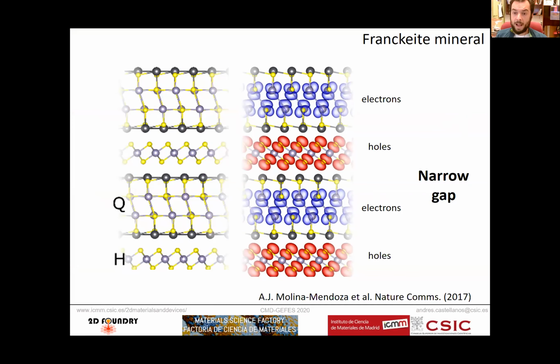One of the first things that you have in this franckeite is, for instance, a very narrow bandgap semiconductor. If you calculate the band structure with DFT, you get a really narrow bandgap. And this is shocking because a monolayer of tin sulfide has a bandgap of more than 2 electron volts. So this is already telling you that the superlattice is not just the sum of the two lattices. And in this case you can see clearly how the electrons and the holes get separated in the different physical layers. The electrons prefer to stay in the tetragonal layers, and the holes prefer to stay in the hexagonal layers.